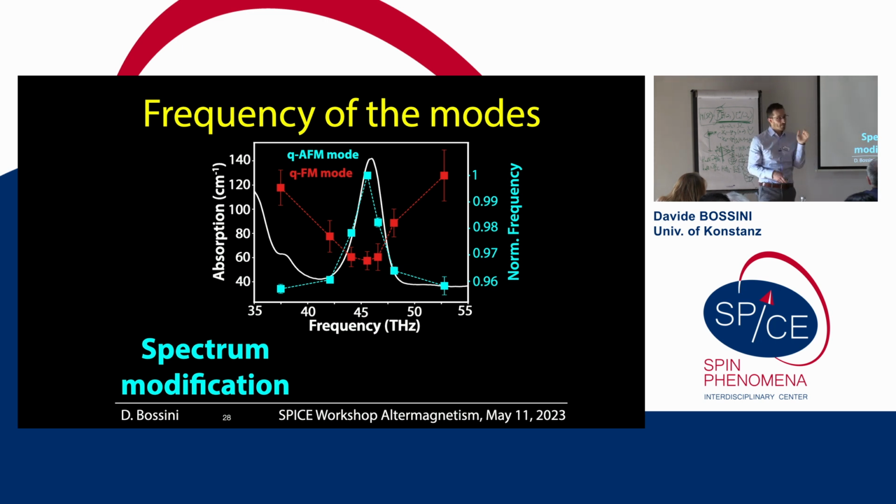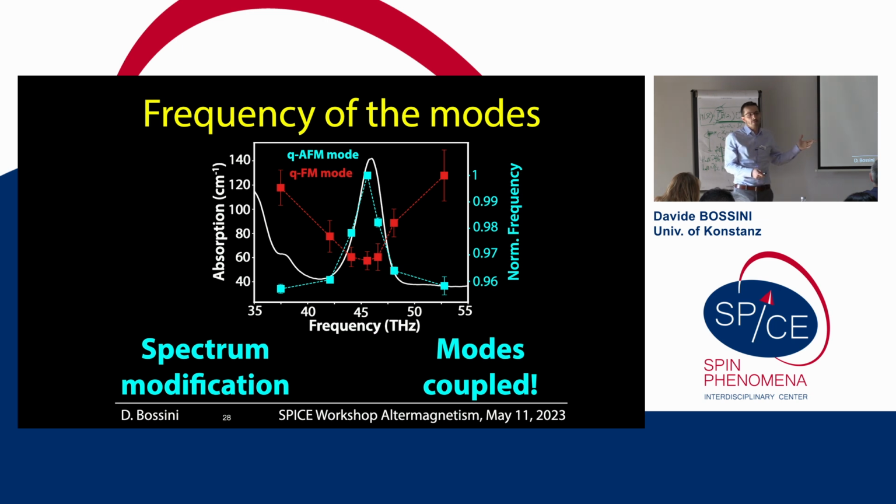In addition, for the specific case of hematite, you can induce exactly that frequency shift, as demonstrated in the literature, if you apply a very strong field, stronger than 5 Tesla, in a different experimental geometry than ours. So, we observe fingerprints, at least, of coupling between the two modes, and what we do to the frequencies is equivalent to applying a monster field of more than 5 Tesla.